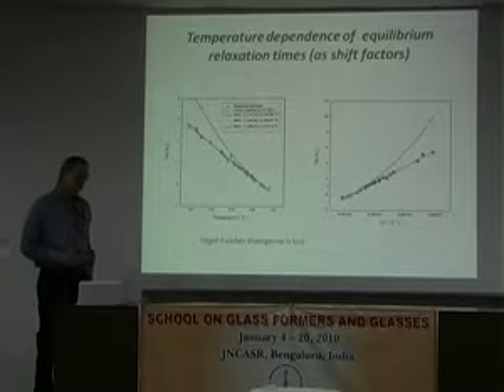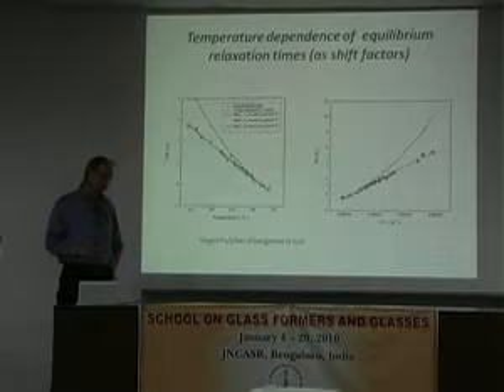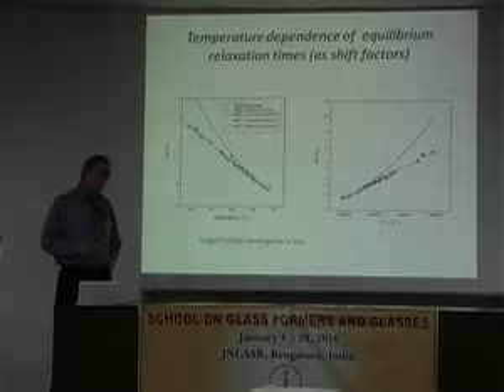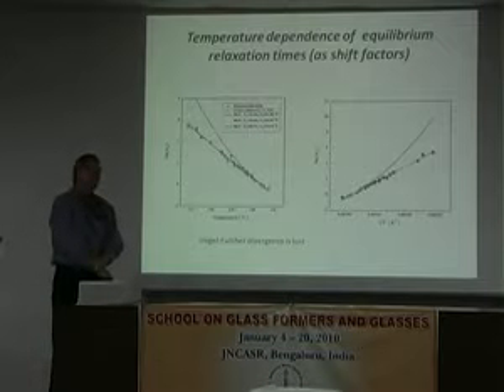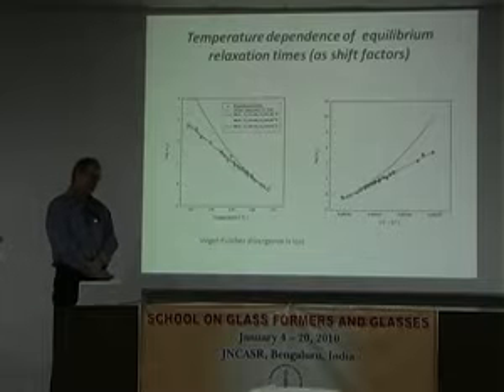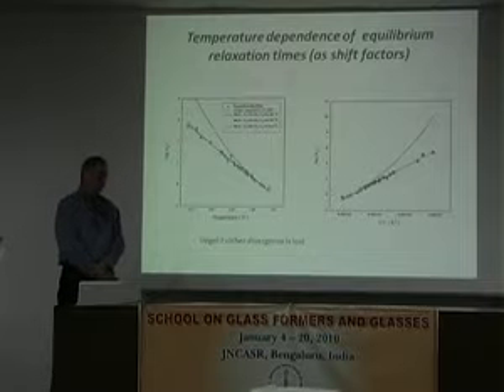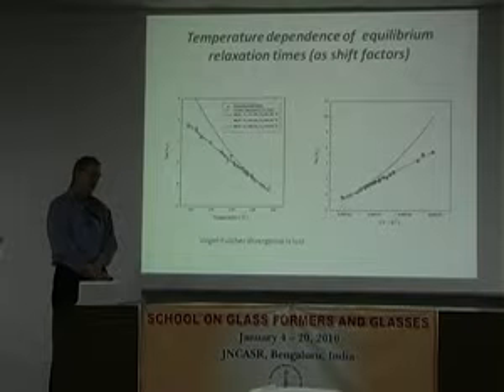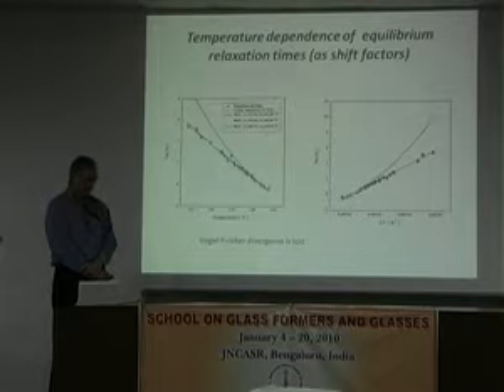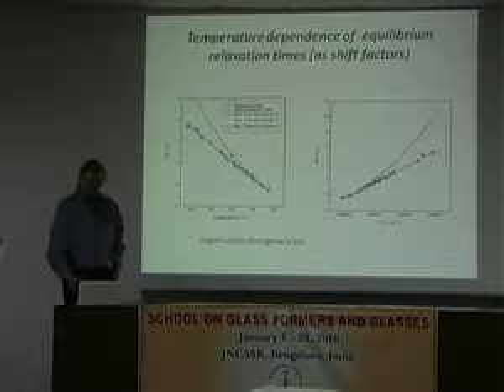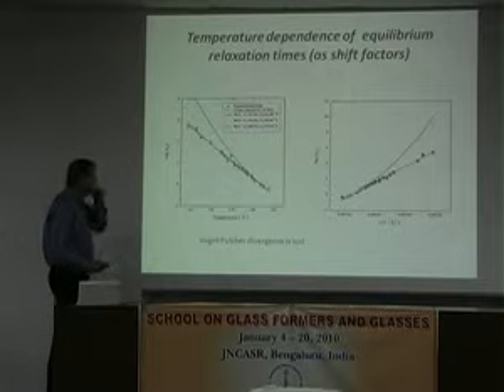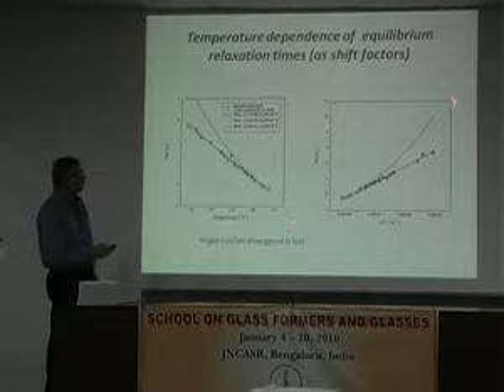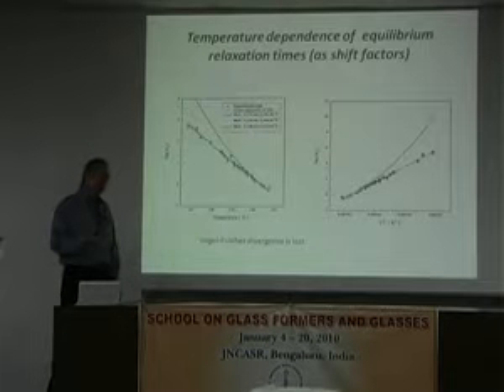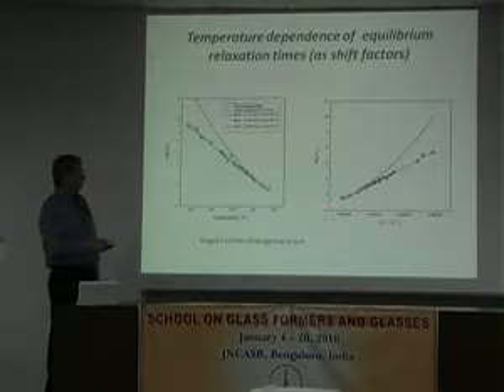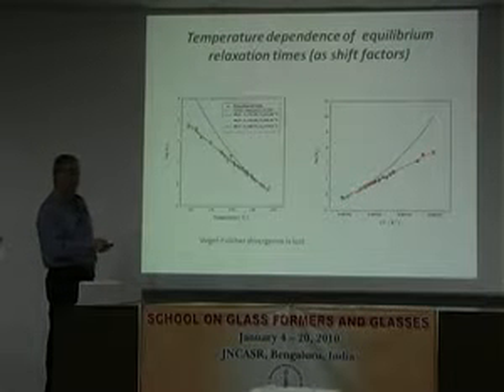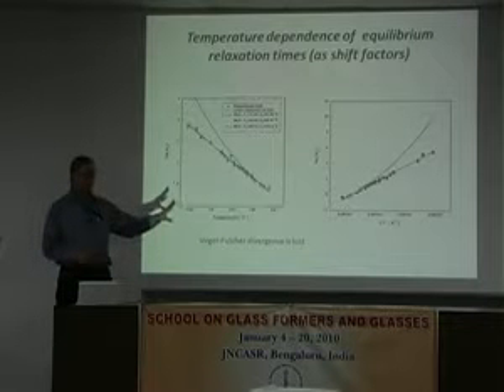Right. No, because you posed the question of whether the shift factor would eventually reach the relaxation times of the liquid by extrapolation, right? Yeah. And so the answer from this graph is negative, but is it negative because the extrapolation is not valid, or is there something else surprising? That distinction I want you to make clearly. Well, clearly the extrapolation of the Vogel-Fulcher curve for this material is invalid. For sure, because this wouldn't fit the Vogel-Fulcher curve, right? Yeah. So for this material, it's invalid.